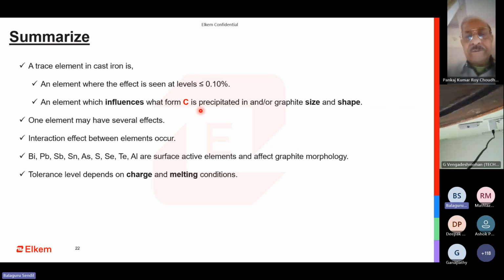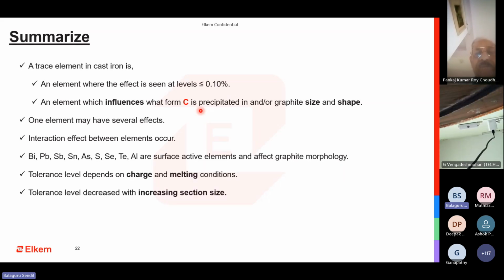The tolerance level of all these elements keeps changing from foundry to foundry, depending upon the melting condition and charging practice. One foundry will operate at even higher levels of trace elements much better than another foundry because of their charging and melting conditions, their holding pattern, and the size of the furnace. The tolerance level also decreases with increasing section size. Again, the same is applicable: when you have thin casting, you might get away with it; when you have thick casting, you might see a problem.